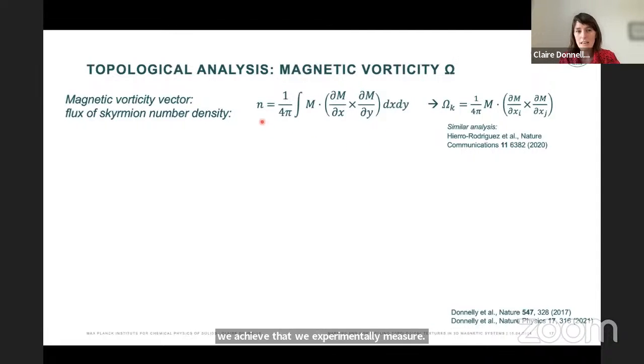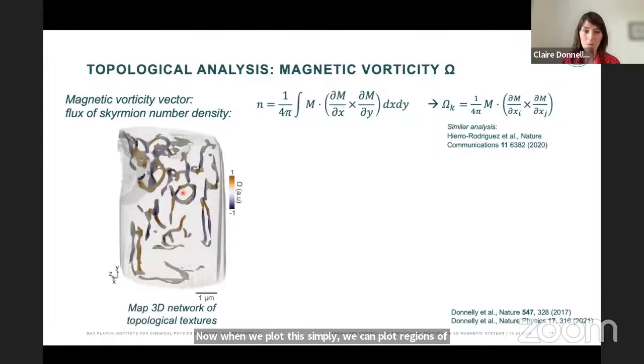And this is essentially by calculating the so-called magnetic vorticity vector. So those of you who are familiar with the skyrmion number, which is shown in this equation here, essentially what we do is we take what's inside the integral of the skyrmion number, and this gives us a vector field that encodes the topology of our configuration. Now, when we plot this, simply we can plot regions of high vorticity in our sample. We can already see that we then have a network, a three-dimensional network of magnetic textures. These are the cores of vortices and anti-vortices.